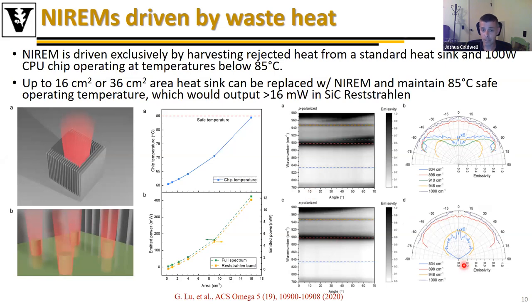Now, we wanted to then explore the radiation patterns of this. Of course, these are spaced at such a distance that we should not have any diffractive effects. And so just to test that out, we looked at the P and S polarized light as a function of angle. And you can see exactly what we would expect is that these are relatively non-dispersive with changing the angle or the momentum. And thus the radiation patterns at any given frequency are either emitted directly into a hemisphere or for some of these dipole resonances, more like a double lobed emission shown here.